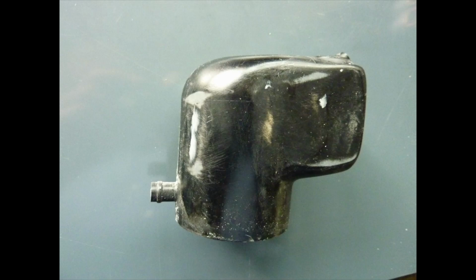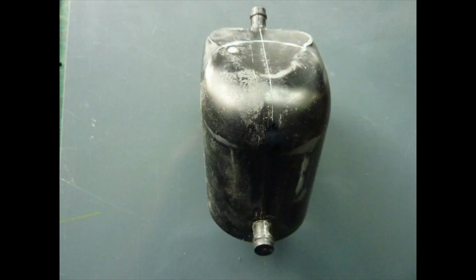The pattern was then used to make a mould into which the alloy would be cast. And here I made a mistake. I should really have used silicone rubber for this mould rather than plaster. It would have probably remained intact for all 8 castings and given a much better surface, whereas the plaster cracked with the heat and for some unknown reason gave the castings a very rough orange peely sort of finish, which needed a lot of work. A false economy. Luckily I'd allowed for a bit of sanding down, but it all took more time.